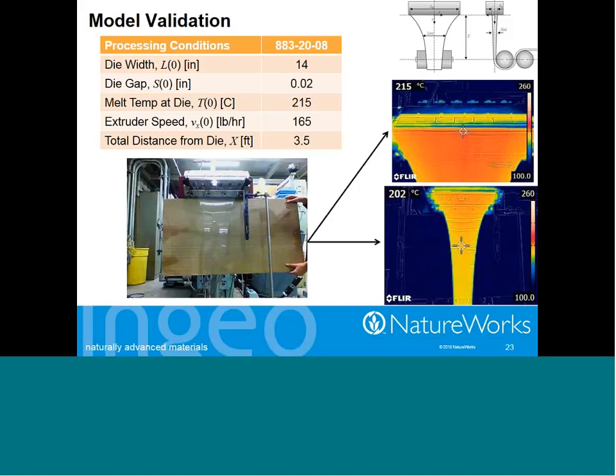So this next slide shows some of the modeling work that we did, where we were keeping track of all of those temperatures and parameters. On the left panel at the bottom of the slide, you can see a melt extrusion, and the cardboard is there to help you see the extrudate come out. And you can see the neck-in of the process there. And on the right, you can see some infrared images to help us keep track of the temperature. And so we could put all of those inputs into a model.